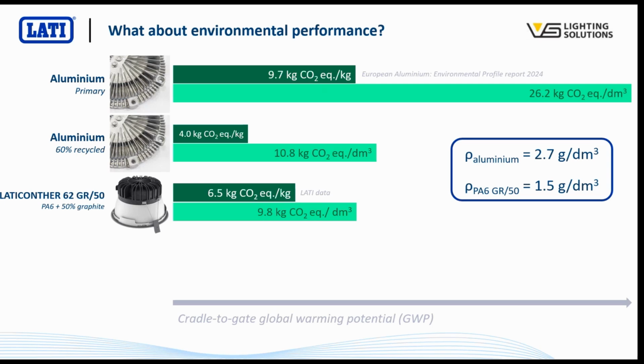It's also before we consider any sort of recycling on the plastic side. So here, of course, we've considered using 60% recycled aluminium. What we find is it's possible to regrind and reuse this material with no loss of mechanical performance, no loss of thermal conductivity. So we could improve this even further by taking some reground material from here, as is common in injection molding, and using that to make new parts.